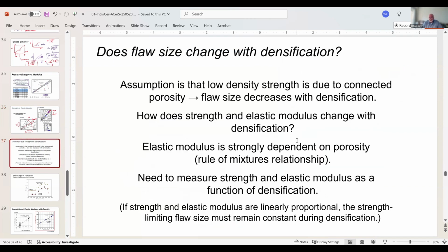So the assumption that has pervaded the ceramic industry for decades is that low density strength is due to connected porosity, that the flaw size decreases with densification. So that porosity is controlling my flaw size, okay? But if I measure the elastic modulus as a function of densification and I measure my strength, how are they related? Because elastic modulus is dependent on porosity, there's a rule of mixtures relationship, which we're not going to go into today. As I densify the system, my elastic modulus increases.